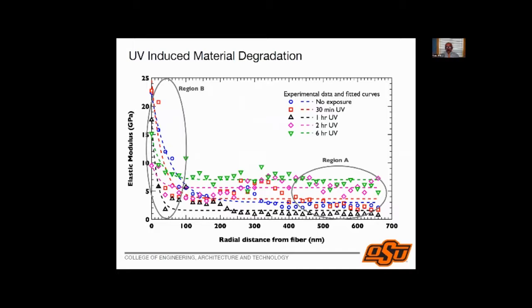So what you're looking at over here is a lot of information, so I'll just slowly walk you through it. These are multiple experiments done at the carbon fiber matrix interface for different levels of UV exposure. No UV exposure is what we looked at earlier. Then after 30 minutes, 1 hour, 2 hours, 6 hours. We are plotting elastic modulus as a function of how far we are from the fiber.